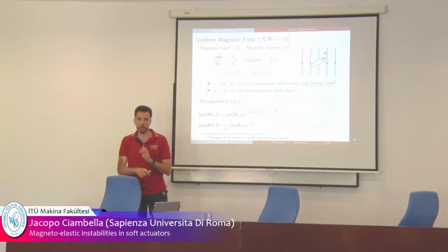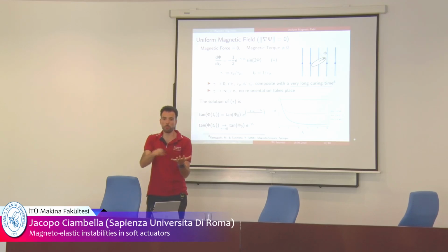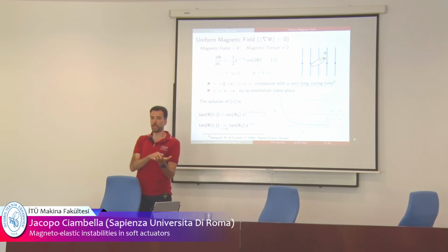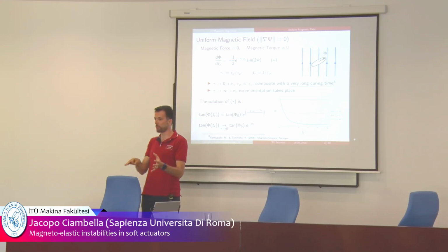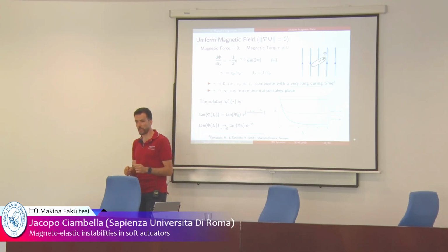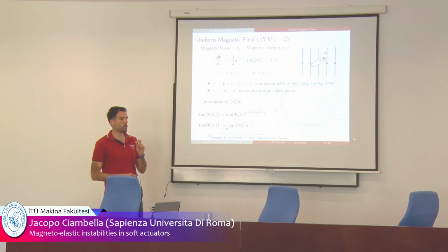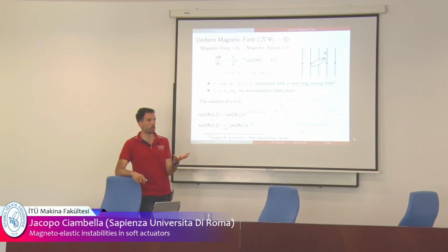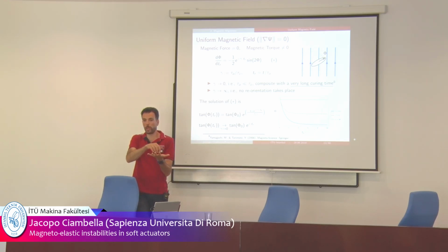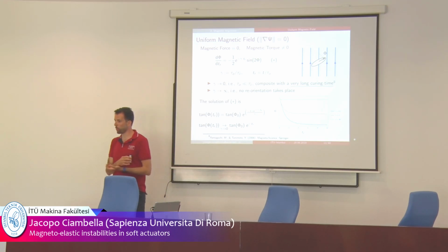If you have a nonuniform field, the particles will start moving. So you will end up having agglomeration of the particles somewhere in the specimen, which is not very good for the mechanical properties. Whilst when you have a uniform field, it's completely different, because you start with a homogeneous distribution of particles, and these particles will only rotate in place. And so we end up having a homogeneous distribution of particles with a tailored orientation. This is exactly what we wanted.